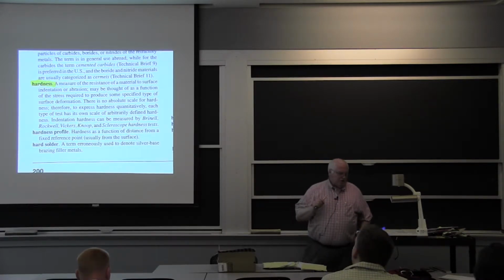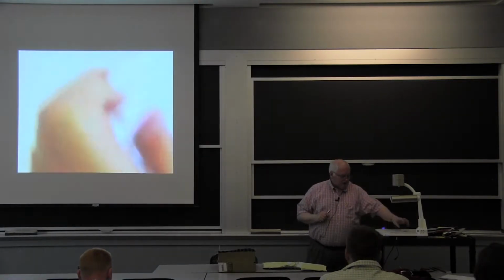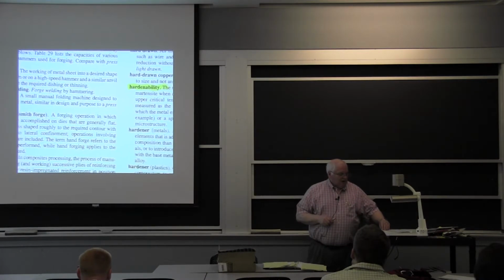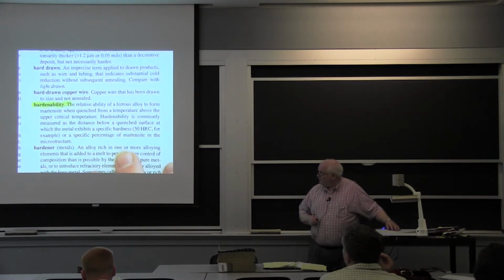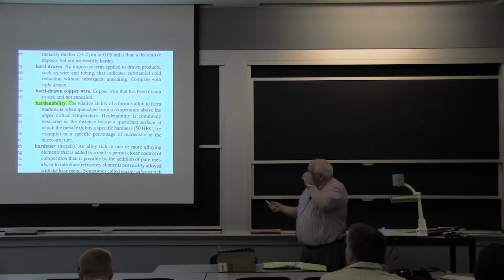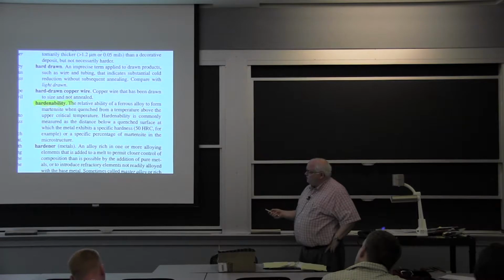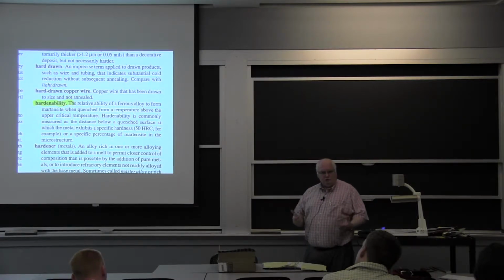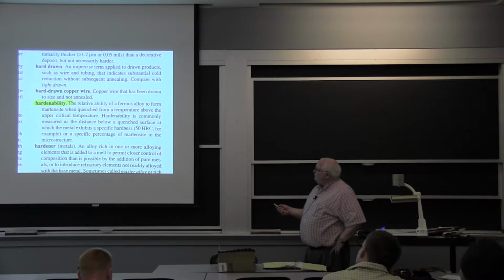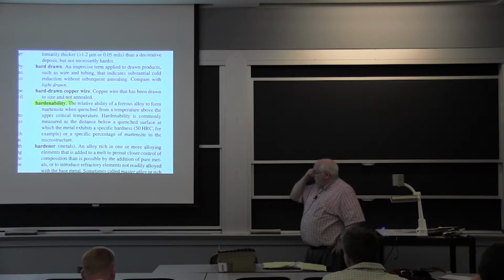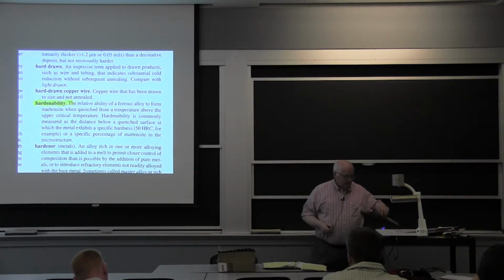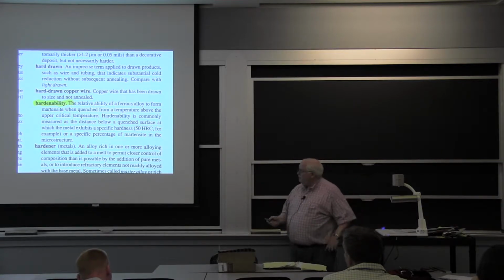So we talk about Brinell, Rockwell, Vickers, Knoop types of hardness tests. So hardness is just a measure of the strength of the material in its heat-treated or non-heat treated condition, whatever condition it's in. Now, hardenability, on the other hand, is the relative ability of an iron alloy to form martensite. Martensite is this non-cubic crystal structure that is very hard when quenched from a temperature above the critical temperature. And you can get hardnesses above 50 Rockwell C, which is sort of like this metal file, probably 55 or 60 on the ends.